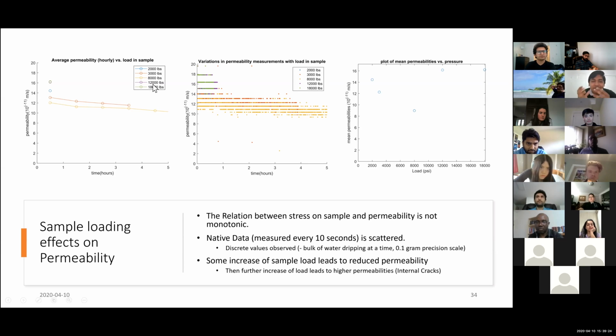But I can't really correlate these loads to the stress inside, basically the tensile stress inside the sample, because these samples, as we have seen before, are failing in tension, not in compression. So this is the plot of mean permeabilities again versus load. We can see that it decreases with load and then it increases again.